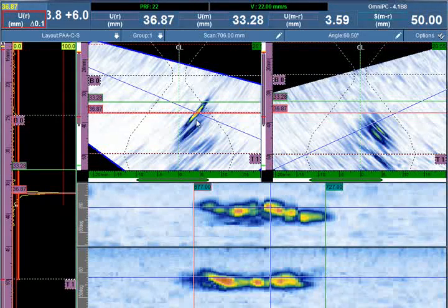These ligaments are smaller than the beam, so no color palette is going to be used to try to do a dB drop technique to identify the extremities. We're going to identify the tip center energy based on the color palette of the signal. So we've identified the deepest or the bottom of the crack,